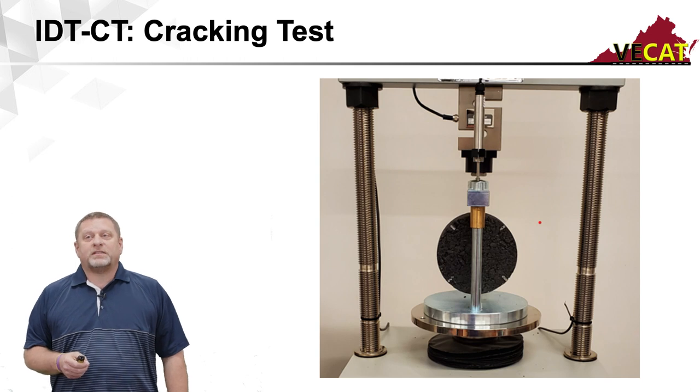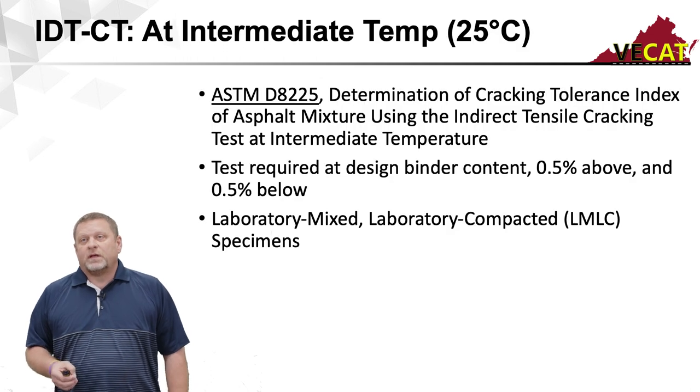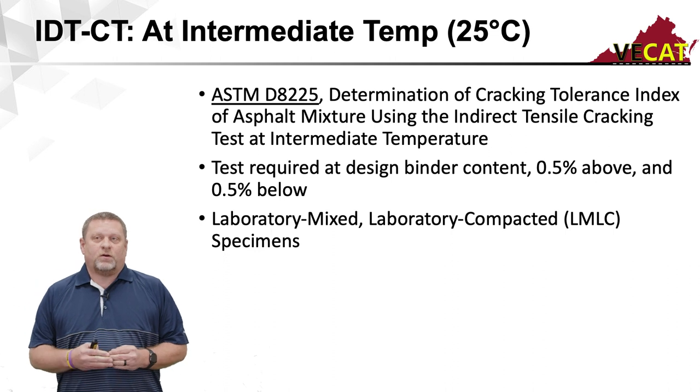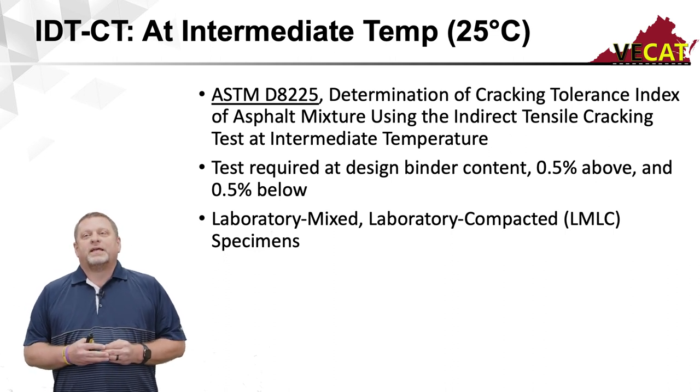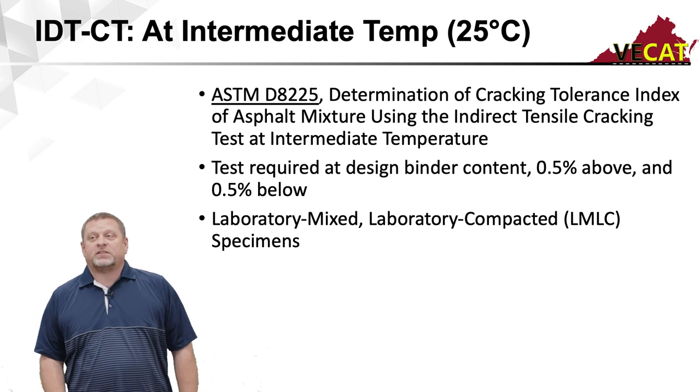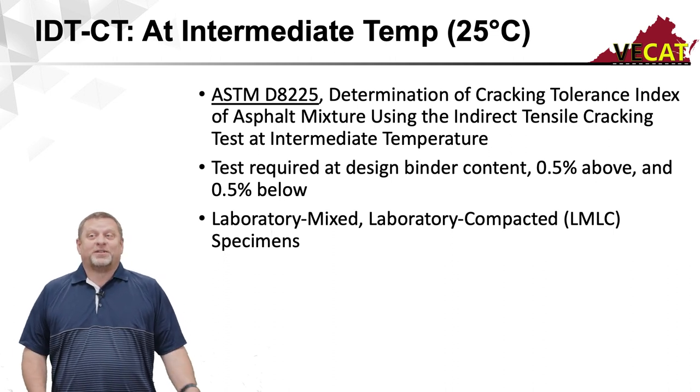Now let's start talking about the test procedures. We're going to start with the IDT CT, which is a crack test. The test procedure that VDOT has assigned or follows is ASTM D8225, determination of crack tolerance index of asphalt mixture using the indirect tensile cracking test at intermediate temperature.